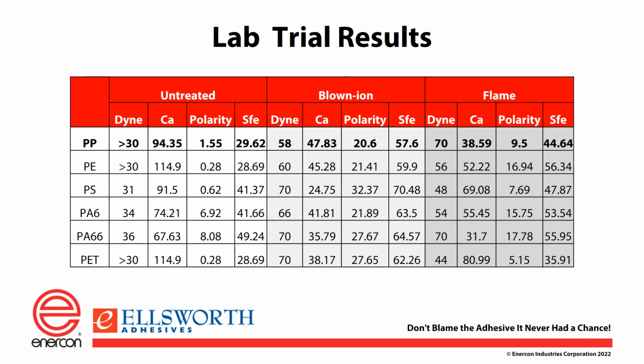I'm not going to go through this slide. I want this to be in the presentation so you can look at it. But what this is showing is how you treat things differently with flame and blown ion and the different results that you get. So the first line is polypropylene. It started out untreated about 30 dyne. Once you treated it with the blown ion, it went up to 58 dyne. But the flame treater in this case did better. It went to 70 dyne.